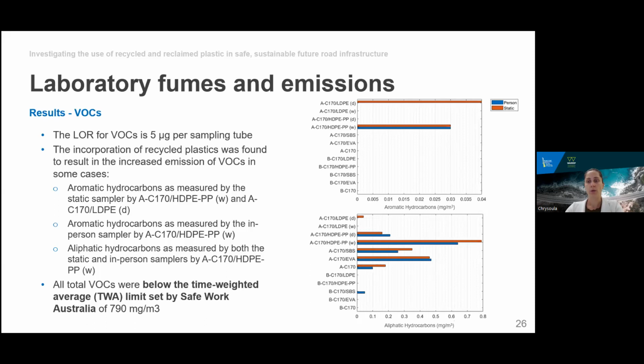Importantly, though, all the total VOCs measurements were significantly below the time-weighted average as recommended by Safe Work Australia. In the worst-case scenario of VOCs emitted during the wet asphalt mixing of HDPE containing binder, the total VOCs were at 0.1% of the Safe Work Australia limit.